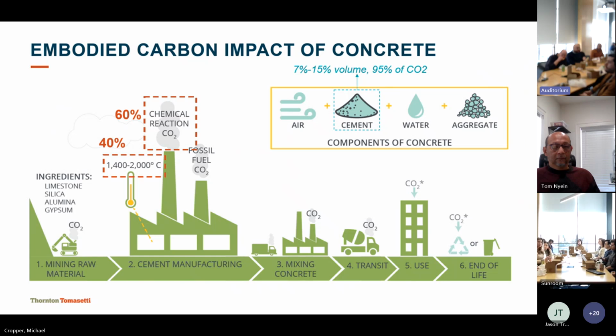It's everywhere. When you think about concrete and the embodied carbon of concrete, just think about cement. So when you hear that there's a higher cement content, that means more embodied carbon. Portland cement makes up about, call it, an average 10% of the volume of a cubic yard of concrete, but it's about 95% of the embodied carbon within that yard of concrete. The reason is that it's all in the cement manufacturing: you've got to heat the kilns to that 2000-degree temperature, and then you're creating a chemical reaction to get the clinker and the cement that is off-gassing and releasing carbon dioxide as well.